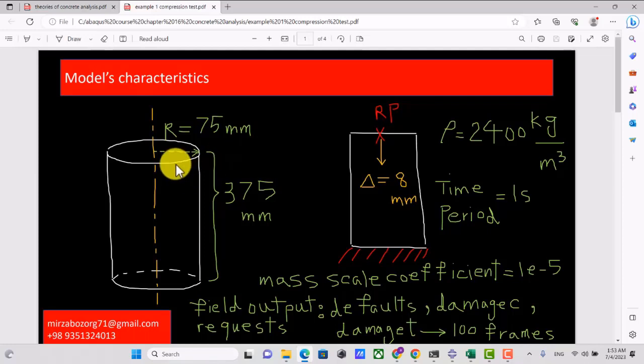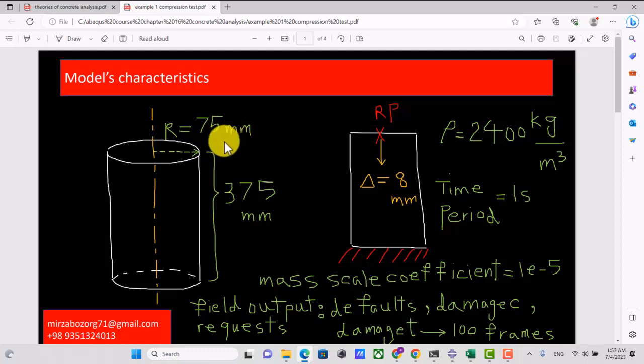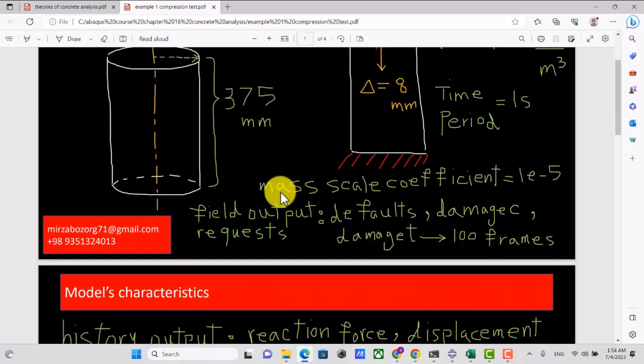This is our specimen, made from concrete. The radius of the cylinder is 75 millimeters and its height is 375 millimeters. We apply a displacement loading. This is the density of concrete. The time period of the simulation is one second, which is not important because the CDP model is not dependent on strain rate by default. We use the dynamic explicit step for simplicity to avoid convergence issues.